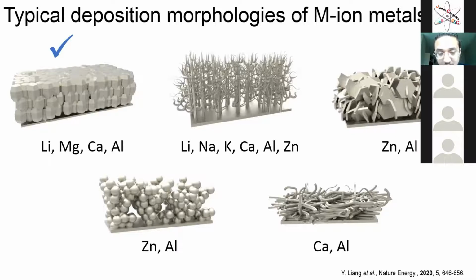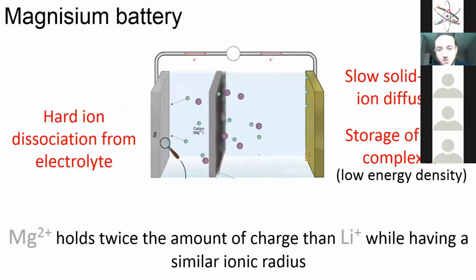Based on this homogeneous deposition and stripping, I will show you an example with magnesium, because there is some interesting work on magnesium. But before, please keep in mind that magnesium holds twice the amount of charge than the lithium ion, while having a similar ionic radius. What does it mean? It means that you will have a hard ion dissociation. It's very hard to find magnesium salts that can dissolve in organic solvents. And then you will have a slow solid state diffusion.